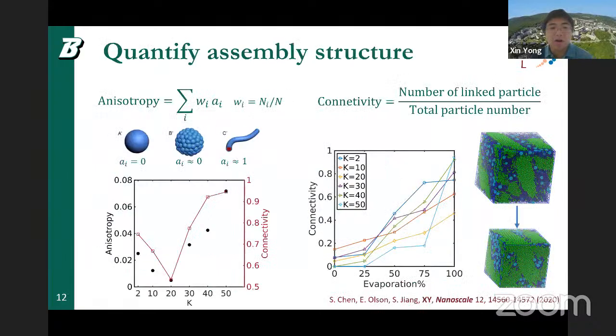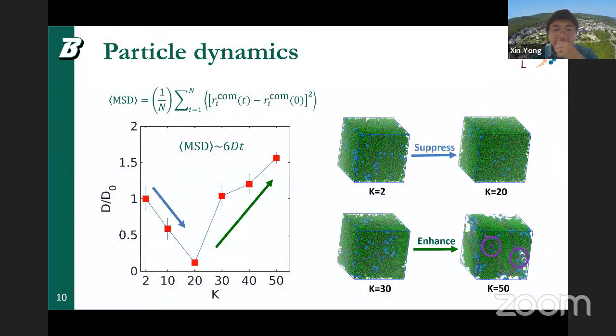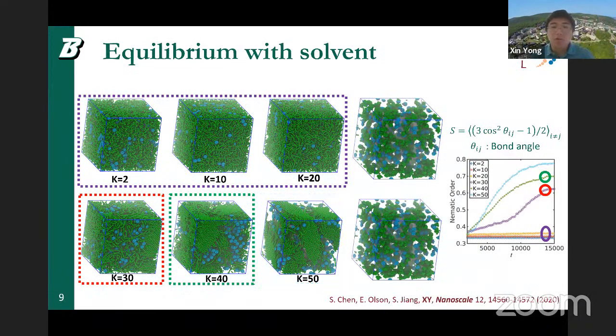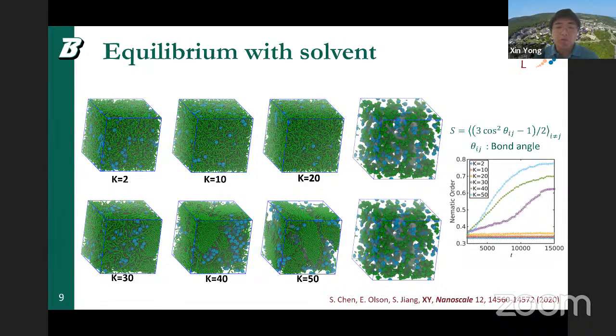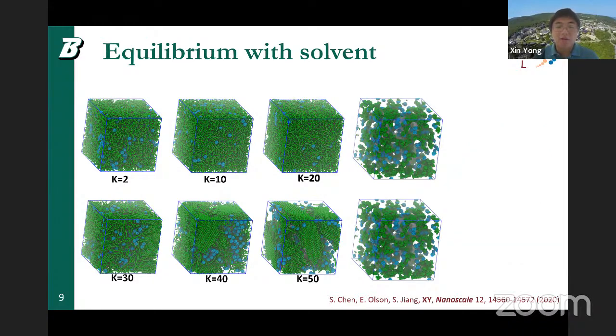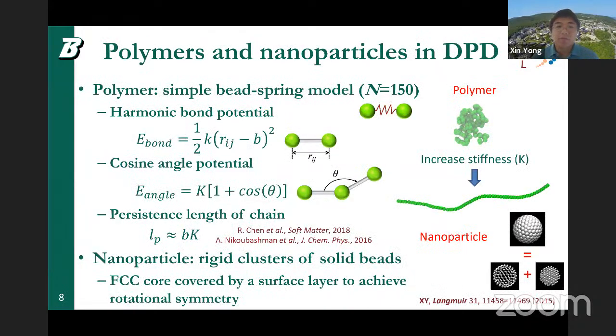That's a great question. For particle size, I don't have it on top of my mind immediately, but let's talk about simulation units first. The particle radius should be somewhere around 1.5, and the polymer length is 150. The persistent length you can calculate based on this relation, where we use B equal to 0.5, I believe, and K varies from 2 to 50. So the persistent length varies, somewhere from 1 to 20, something like that. For a very rigid polymer, it's pretty much like a bendable rod.